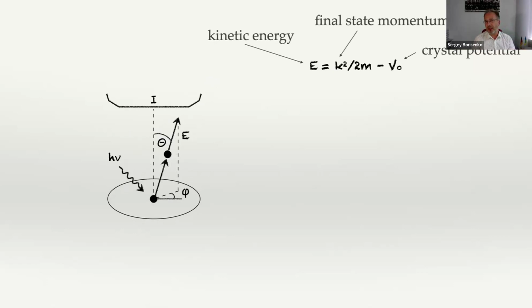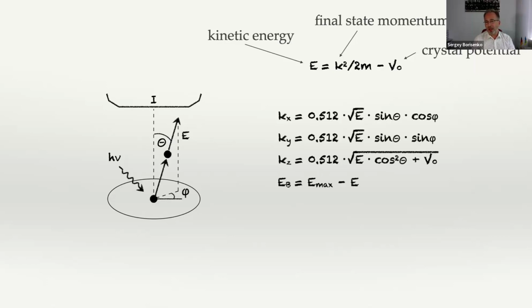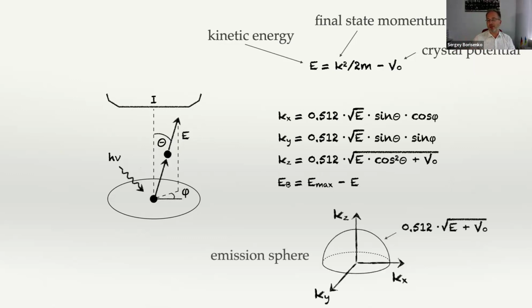And this is the very simple conservation law, which shows that the kinetic energy of the photoelectrons is related to the energy in the crystal in a very simple form. It is the simplest approximation, which I took from very old photoemission work. From this directly follow the main equations of the method, which allow us to relate these measurables, kinetic energy, angles, and photon energy, with elements of the K-omega space, as we called it once, or K-binding energy space. So there is a four-dimensional space.